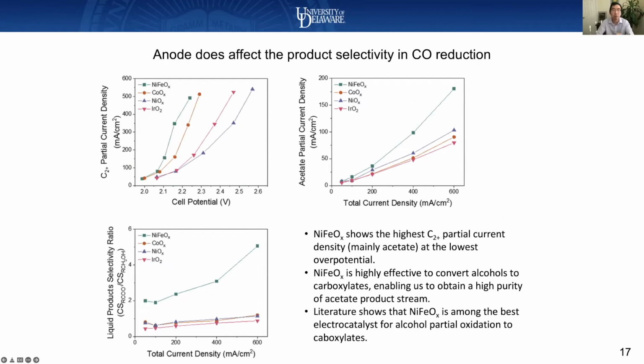So how do we prove this? What we did here is we use different anode catalysts. For example, iridium oxide is a very typical standard for any system. And the nickel iron oxide is the one we actually use in this particular study. And what we found is, in terms of cell potential, nickel iron oxide actually is way better than iridium oxide.